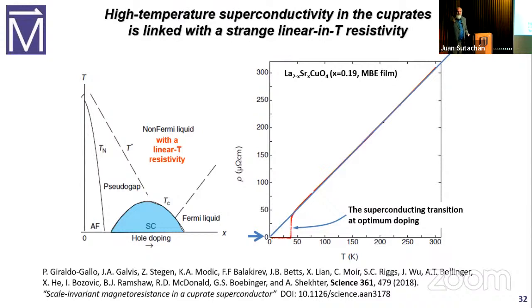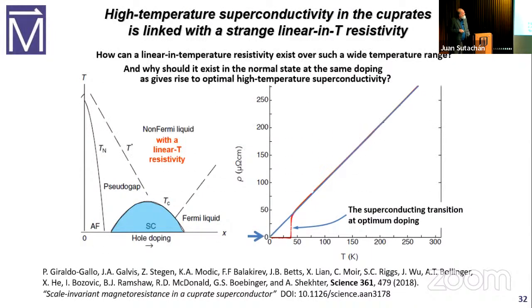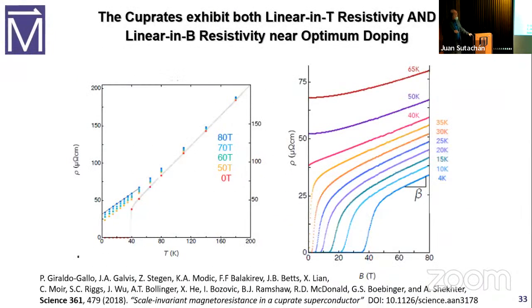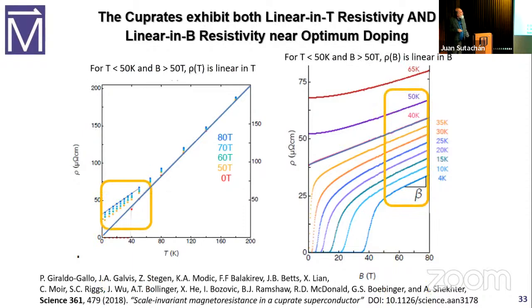So now we've got two strange things happening in the non-superconductor right when the superconductor is optimized. And one of the things that Giraldo-Gallo and Galvis discovered is that you not only have linear in temperature resistivity, you have linear in magnetic field resistivity at optimum doping. And nobody understands why that happens either. So there's still plenty of mysteries about what's going on. For an entire regime below 50 Kelvin and above 50 Tesla, the resistivity versus temperature is linear in temperature, and the resistivity in the same range in field is linear in magnetic field.